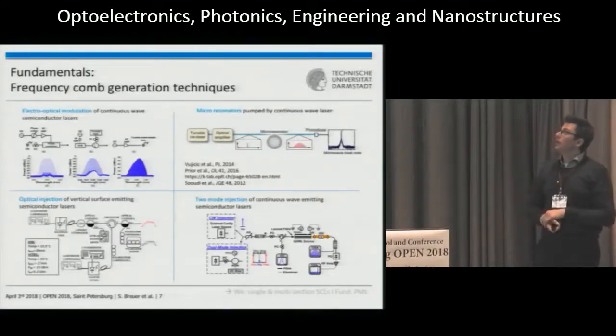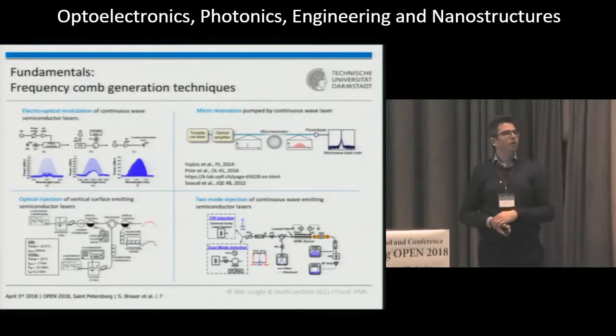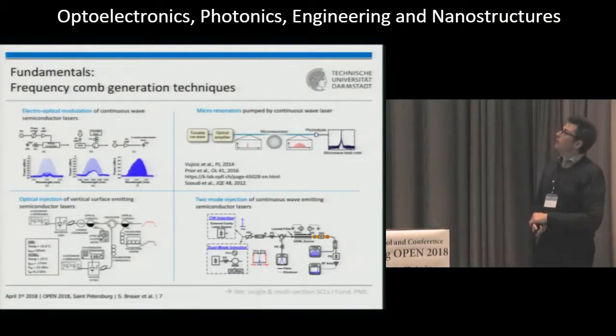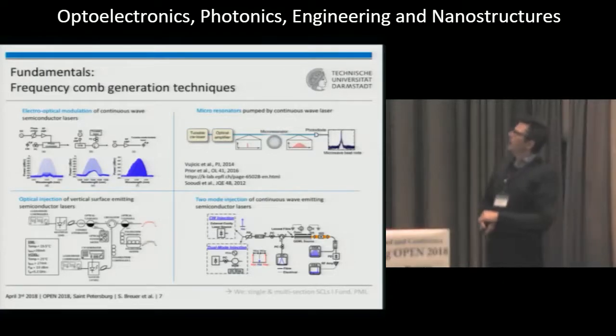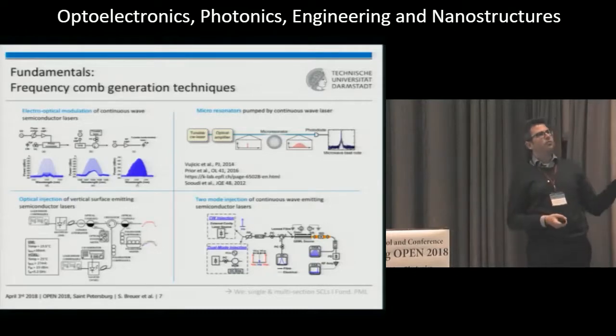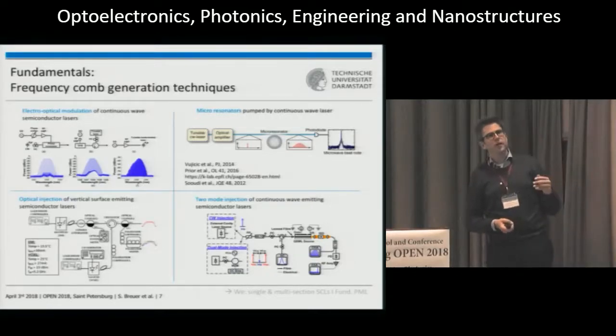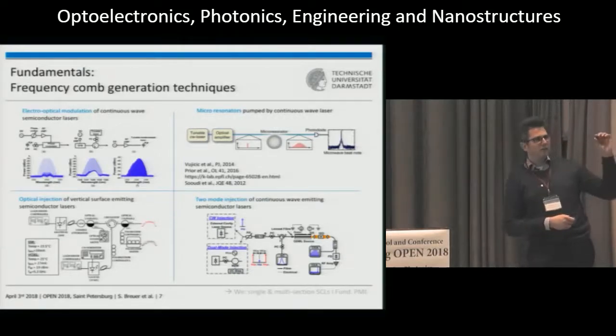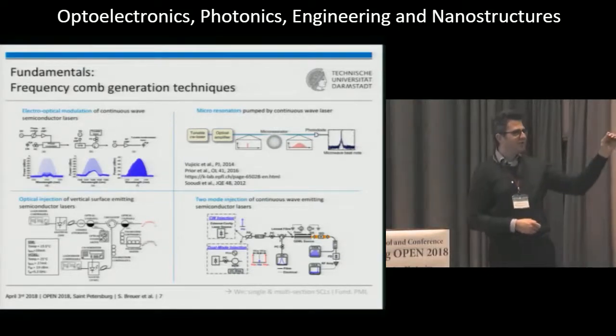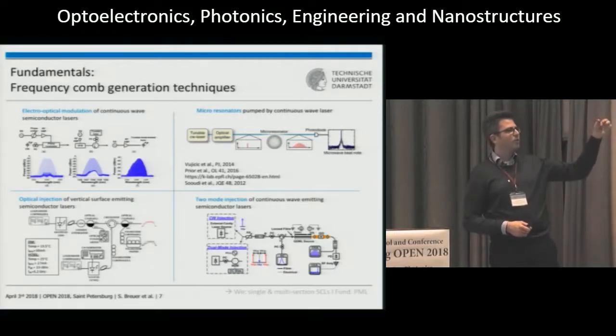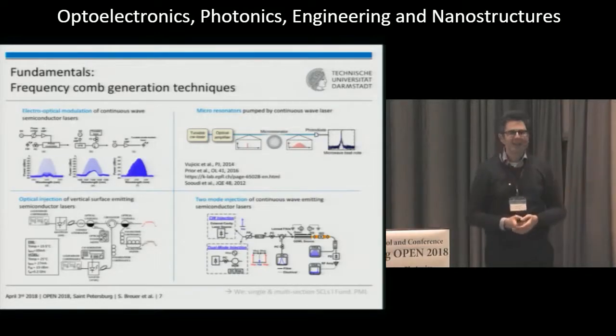And also here at the academic university, Professor Chukov is pioneering this: microdisc structures in semiconductor materials. It's, for example, optical injection of vertical cavity surface emitting lasers. There are actually 2 startups right now in Europe that are commercializing a very simple technique. It's actually a vertical cavity surface emitting laser, just this, with a narrow aperture, like 10 micron diameter. What they do is electrically modulate this VCSEL with a rectangular current form, and this gives a stable frequency comb. So they can package it like this.